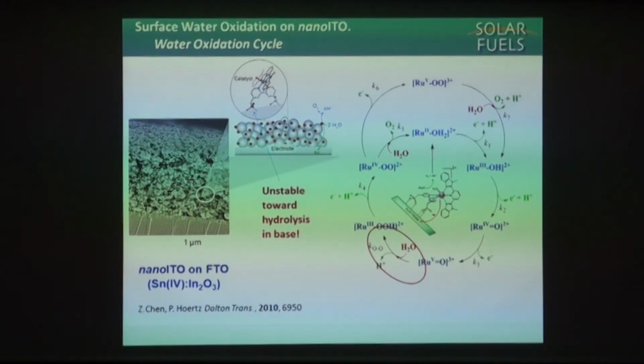And here, in fact, is a scanning electron micrograph. This is an underlying transparent conducting oxide. Notice all these nice particles. This is what a TiO₂ film would look like, but this is not quite that. What this is are nanoparticles of one of these transparent conducting oxides, namely tin-doped indium oxide. So these little nanoparticles, this film conducts electricity. So we can coat that with our catalyst. You can see through it, you can do spectrophotometric experiments, control the potential, and you can do water oxidation catalysis, but you just increase the surface area by 500 to 1,000. Great stuff, same mechanism, small problem, surface attachment, right.